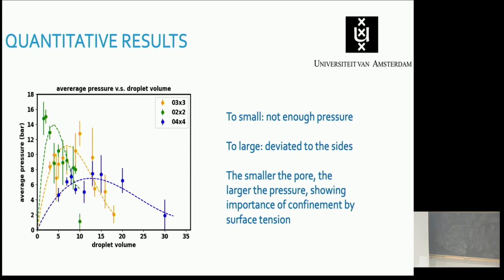We get very small capillaries. If they're too small, basically the water won't touch the walls. So if there's too little water, it won't touch the walls, it won't exert any pressure, and nothing really will happen. But if we have too much water, again, we have very little fracture. And so we think that is because the force is deviated to the side. And the smaller the pore, the larger the pressure. And so that explains some differences that people have seen for different types of porous material.